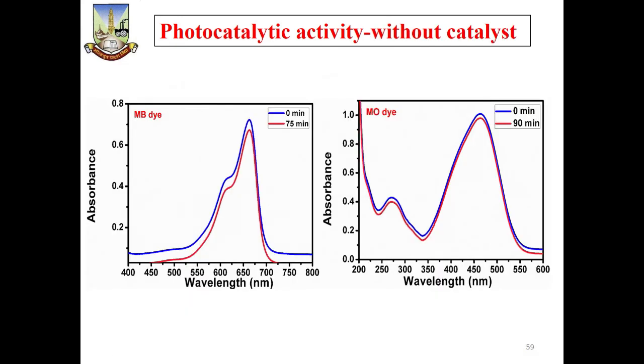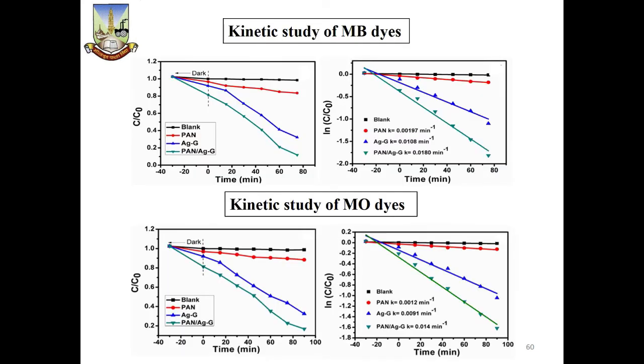So for photocatalytic activity without catalyst, there is no degradation up to 90 minutes. Without catalyst, the dye remains as such in the water solution; no degradation of methylene blue or methyl orange is possible without any catalyst. This is the kinetic study of methylene blue dye and methyl orange dye. Both show a pseudo unimolecular first order reaction. From this kinetic study we came to know that it is pseudo unimolecular first order.